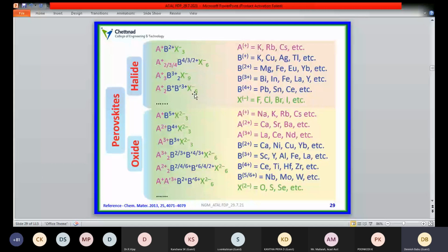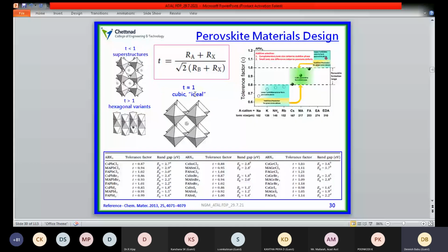The tolerance factor relies on the ionic radius of the A site atom, the B atom, and the X halide atom. If the tolerance factor is approximately equal to 1, then only it will be an ideal perovskite material. If it is greater than 1 or less than 1, it will lead to some other structures that will not be useful, but they are sometimes useful for other applications.